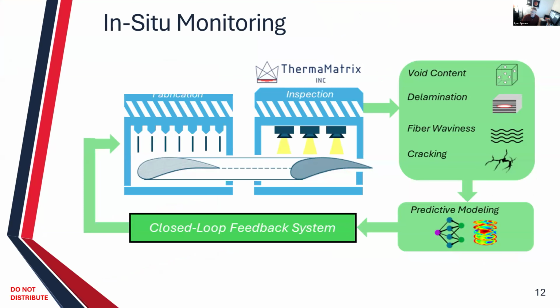Now we try to position ourselves to also support in situ monitoring. Our camera systems can be embedded in the manufacturing process and will allow that rapid inspection. Specifically within composites, we're trying to monitor void content, subsurface delaminations, and fiber waviness by monitoring fiber direction and misdirection, and again, surface and subsurface microcracking. We want to provide a closed loop feedback system where we support predictive analysis to help with that closed loop feedback and really provide a reliable and sustainable manufacturing process.